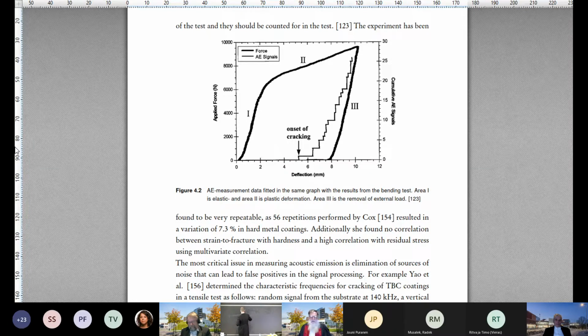What I'm seeing here, the interesting thing, is that the onset of cracking is occurring. Now, of course, this is a bending test, but I see the onset of cracking occurring in region 2, which is presumably analogous to pop-in if we were talking about fracture mechanics, or plastic deformation. That's not entirely correct because it's a bend test, but I can see a nice correspondence with regards to cracking mechanisms.